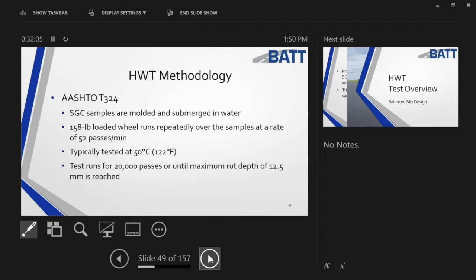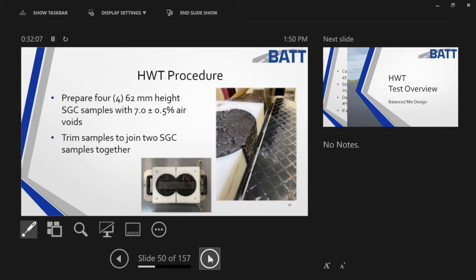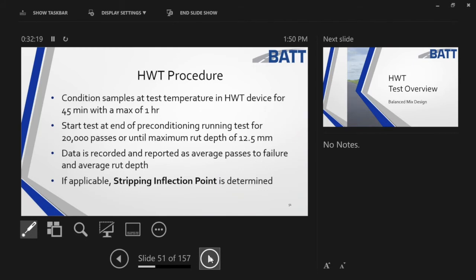And again, on this one, we do not age to 4 hours. We're aging to two. Why is that? Worst case scenario for rutting is less aging. You do have to make a little trim on this sample, as you see, to butt these two samples together. Again, 62 millimeters tall, and you're making them to 7% air voids. This is just going over the conditioning procedure.